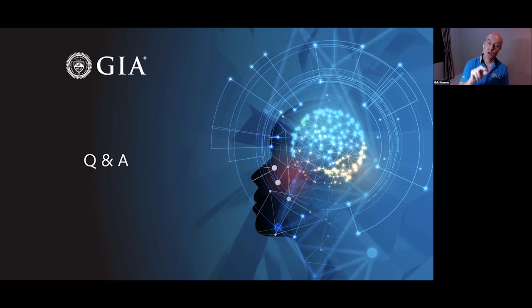And then there were two other pearls. I didn't really have the time to point them out in more detail, but for those who may be more observant, or if you want to replay the video and check later, there were two other pearls which showed very weak fluorescence as well, and those were bead cultured pearls. So in that necklace, we found one freshwater non-bead cultured pearl, and two saltwater bead cultured pearls, and the rest of them were natural pearls.